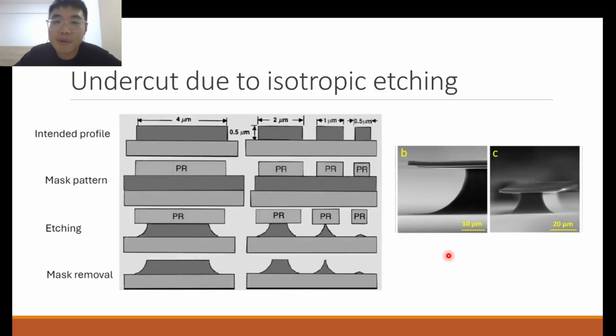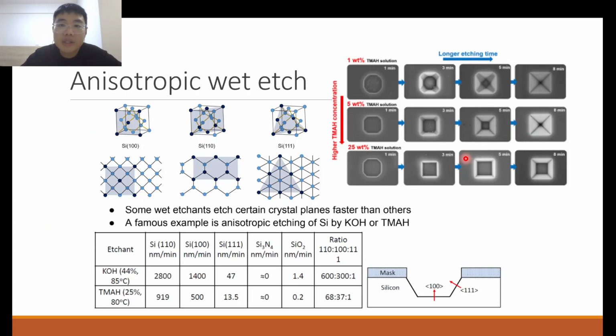However, the problem with isotropic etching is that it causes this undercut, because of the curvature of the surface with the etch, because it's etching in all directions equally. So what I have is this undercut, which may be a good thing for certain purposes, but in many cases it's also not a good thing. So we mentioned so far that wet etch is normally isotropic. However, is there a situation where wet etch can be anisotropic?